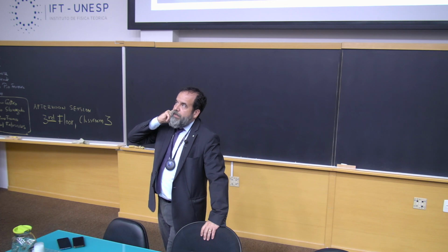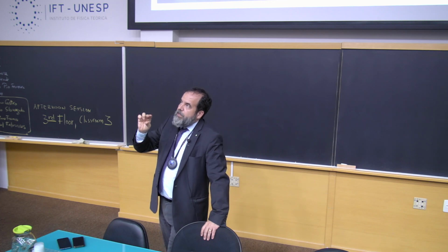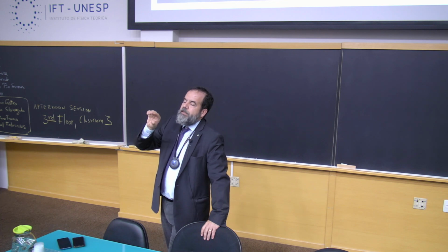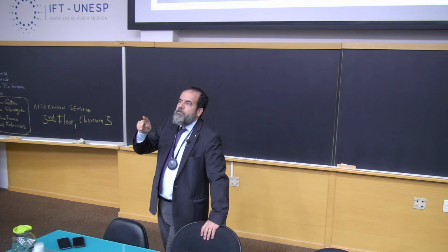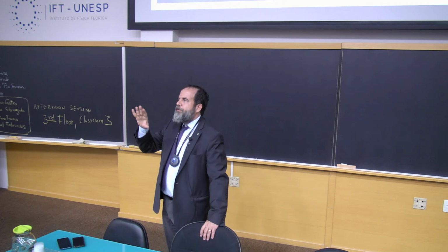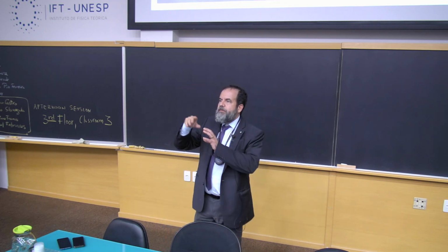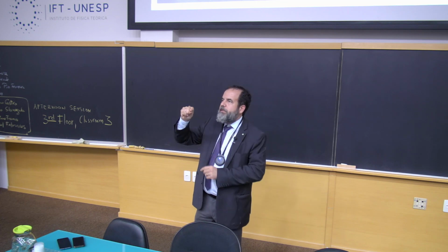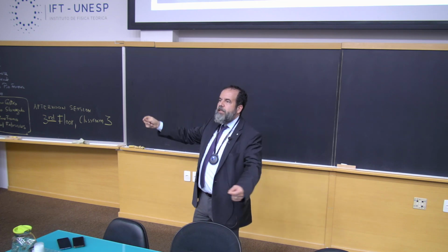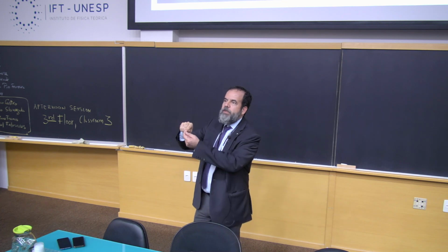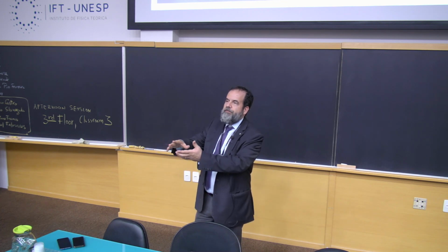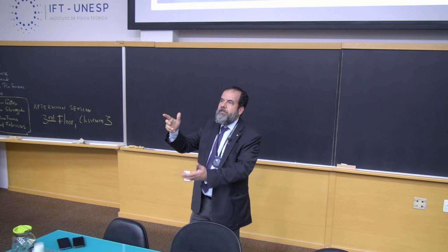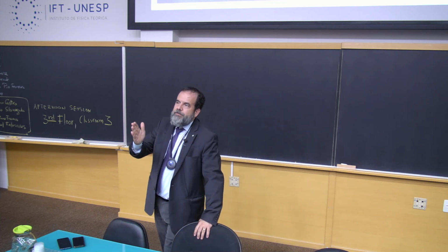Okay? And the other thing is that with silicon, the trick to make the charge separation is by this internal electrical field. And this is quite okay, but sometimes not so good. So you have a lot of drift diffusion. So again, I have to have a very perfect material to be sure that these charges that are photogenerated will not find another pair and have a recombination, and then I lose the excitation I just created. So the perfect, the best.